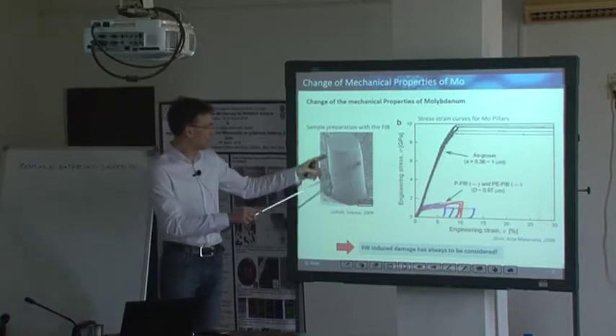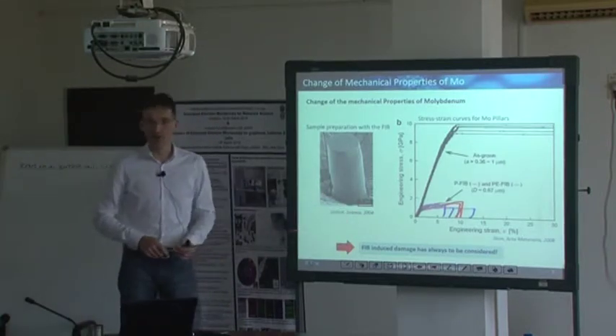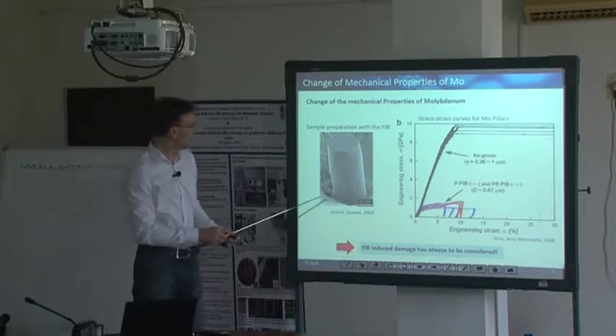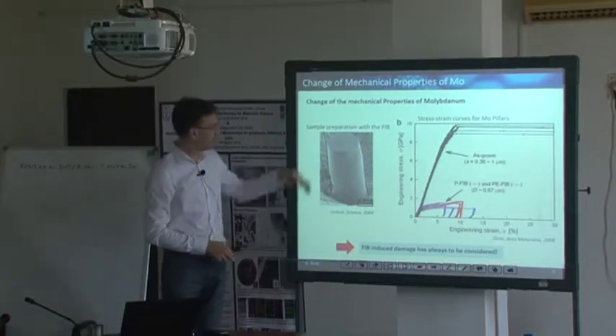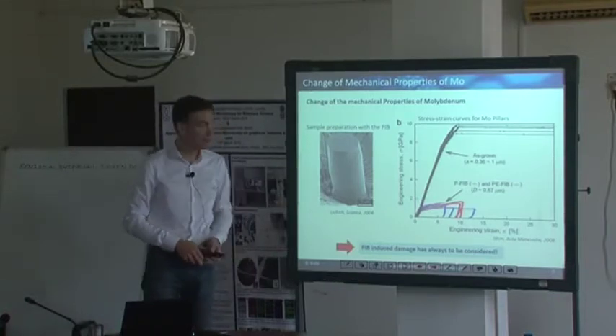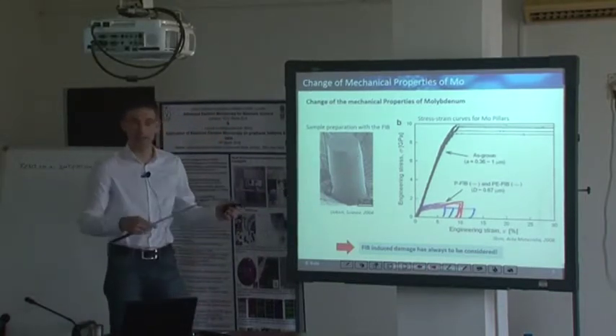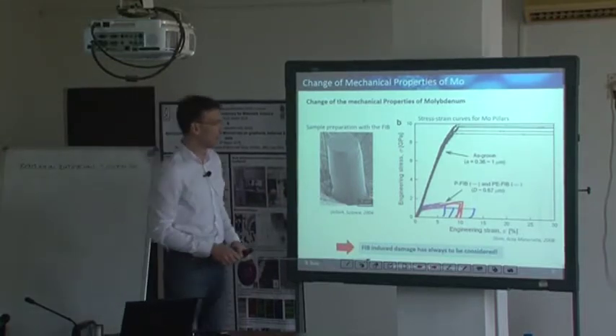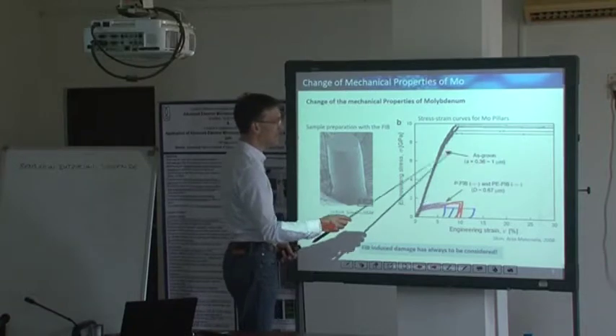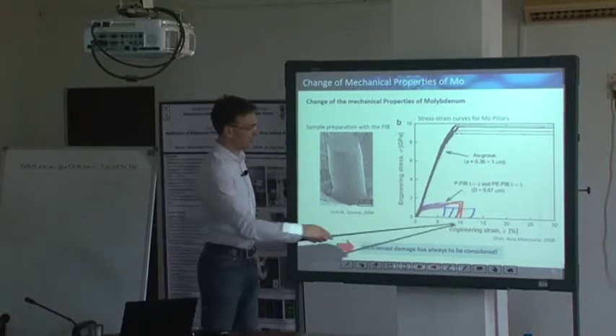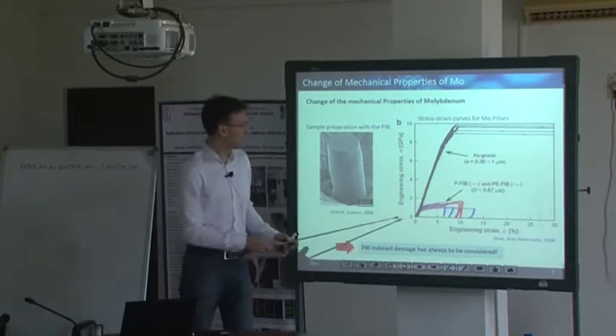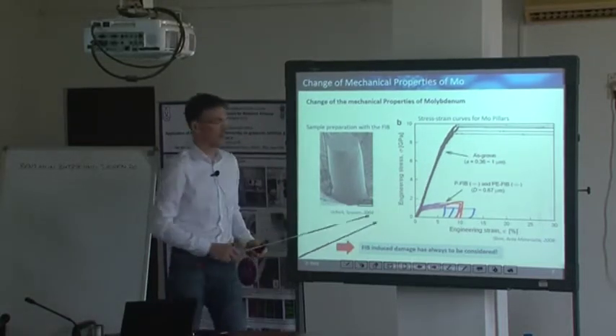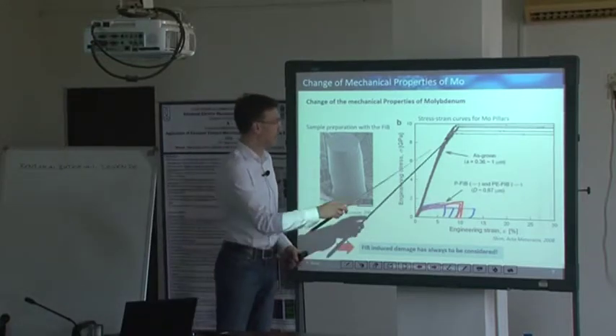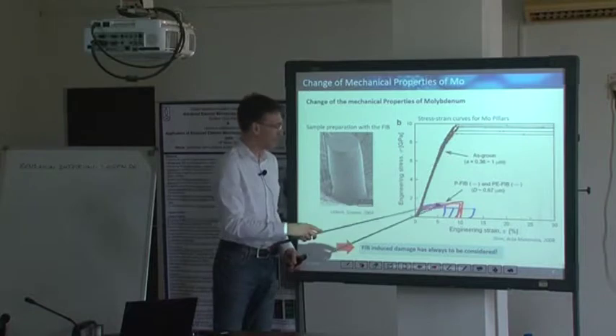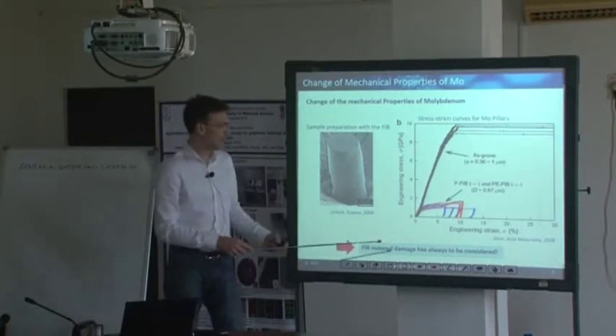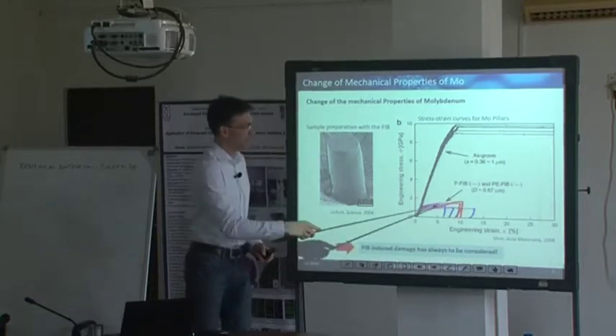So these are some pillars. This is one pillar which is generated just by this gallium ion milling. This is already plastically deformed, so there was some stress applied from the top. This is a common pillar test. The glide planes here are at an optimized angle of roughly 45 degrees or so. And here you can directly see how the sample behaves. So this is just the stress-strain curve of the material. This is somehow, let's say, the bulk or the undamaged material. And you can see these stresses exceed the observed stresses in this particular experiment or in this application by far, you know.